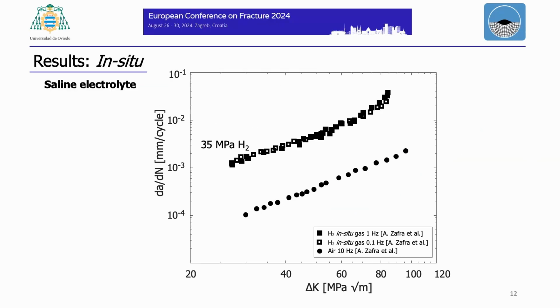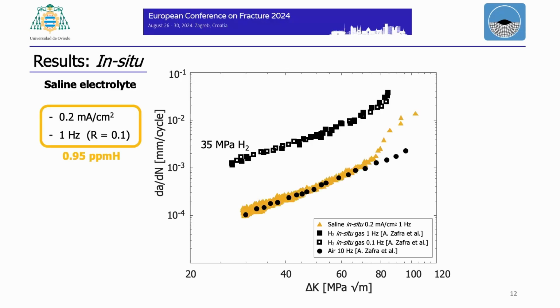Regarding the in situ test, let's start with the saline electrolyte. First, we use a current density of 0.2 and 1 Hz, because in the in situ gas test, we observed that with the 1 Hz frequency, it was enough to see embrittlement, and also when we reduce the frequency, the result was the same. So in gas, the frequency has no influence. So that's why we started with 1 Hz. But in the in situ test with the saline electrolyte and the electrochemical condition, for 1 Hz and 0.2 milliamp per centimeter squared, the result was the same as for the air test.